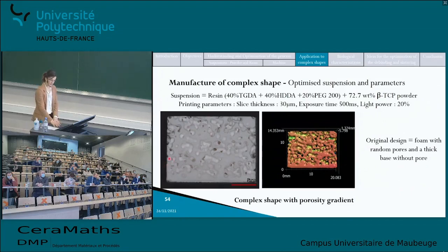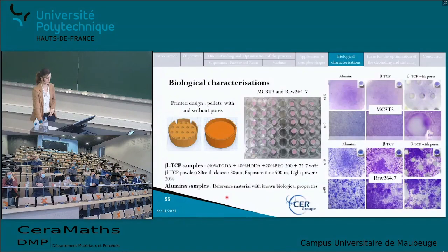The next step was then the biological characterization, again because the goal of this optimization was to use the samples for bone regeneration. So I chose two different designs, a β-TCP pellet with pores and a β-TCP pellet without pores. And I printed them with the optimized composition and the optimized machine parameters. And I used alumina samples as a reference material because of their known biological properties.